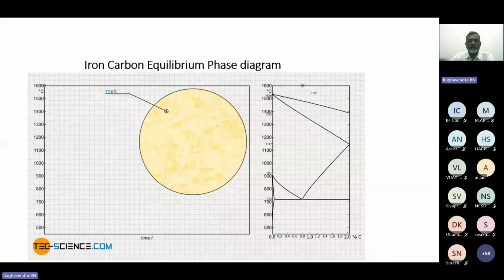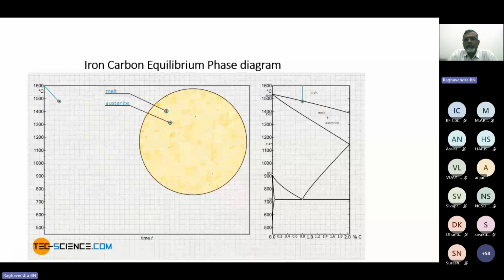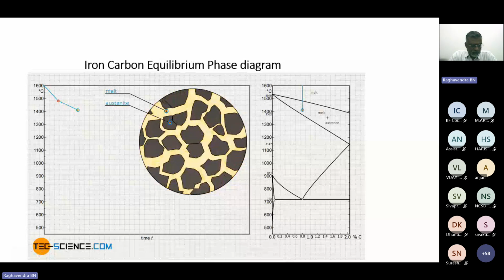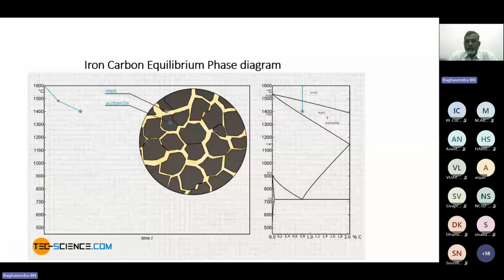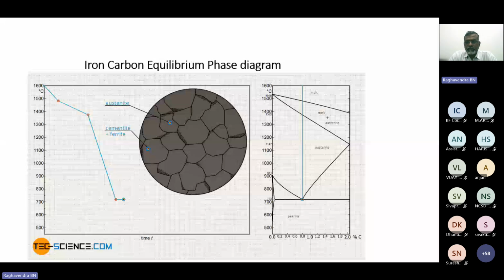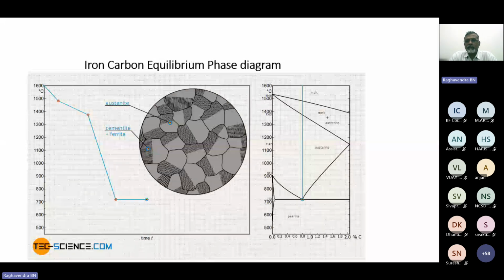For example, take 0.8% carbon. It is completely liquid now. Then this is liquid plus austenite. Now it has become completely austenite. Austenite is an FCC structure. When it touches 723 and below that, since the carbon is more, it will completely transform to a pearlitic structure. Pearlite means the alternate layers of ferrite and cementite. This is how in the iron carbon equilibrium phase diagram the phase changes happen at different compositions.